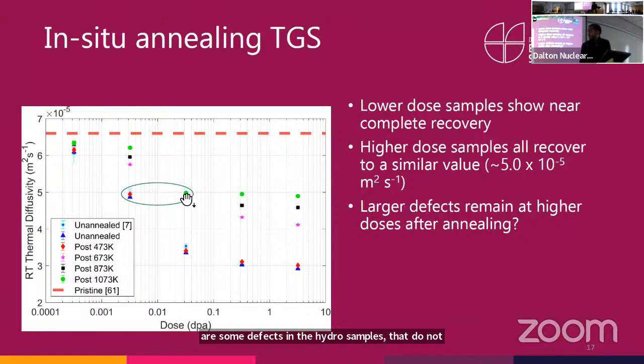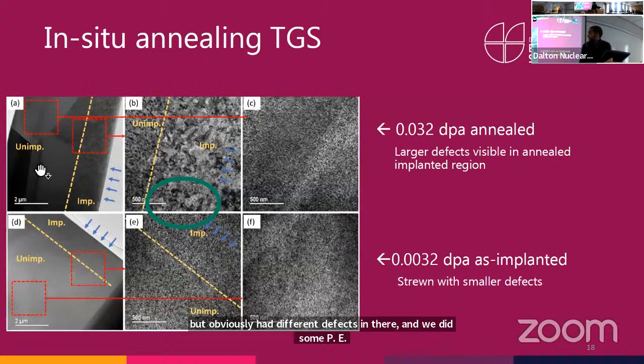And so then we picked out the annealed 0.032 dpa sample and the as-implanted 0.0032 dpa sample, because they had the same thermal diffusivity, but obviously had different defects in them. And we did some TEM. So this is the 0.032 dpa annealed, and this is 0.0032 dpa as-implanted.